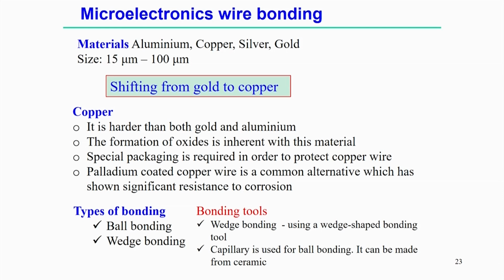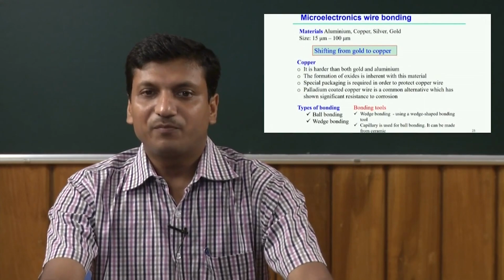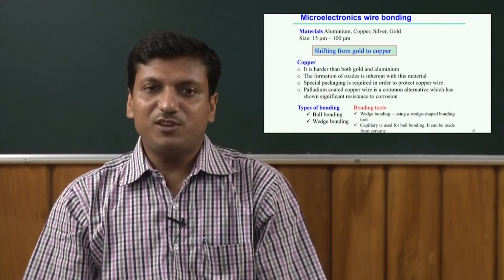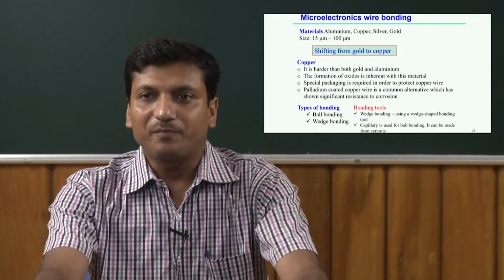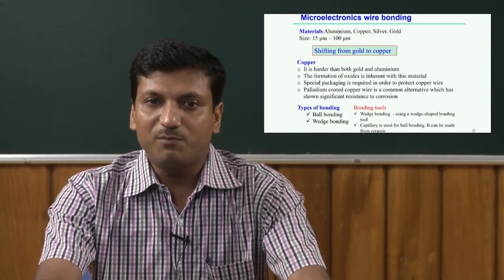This is the positive point, but there is a formation of oxides which is inherent with this material. So to protect this joining process, the bonded joint, special packaging is required in order to protect the copper wire. But palladium coated copper wire can also be used, and is commonly used as an alternate, which has been observed to have significant resistance to corrosion. So that's why now copper can be a replacement for gold, of course with some negative sides, but still it is comparable to that.